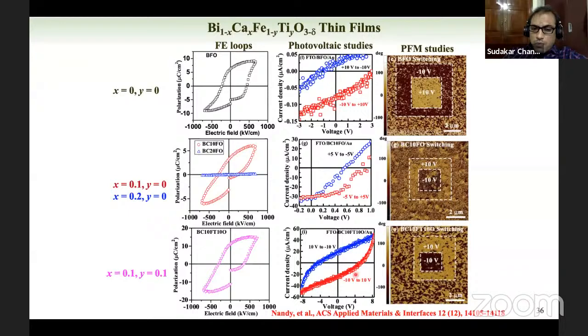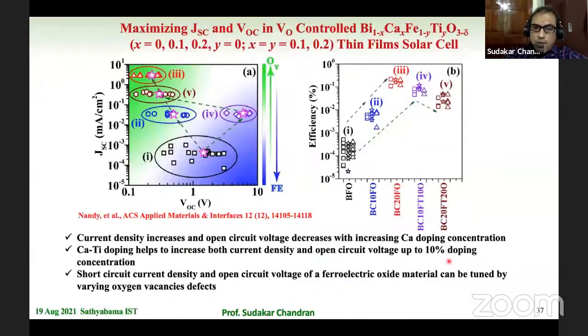That was the beautiful study that we showed, and we did a large number of device tests, and we found that the efficiency in an optimized condition can be close to 0.2%. Remember, these are all polycrystalline thin films, done by a very simple process like spin coating, but we do get efficiencies close to 0.2%, which is very high, and that kind of high efficiency is not reported on this particular material.